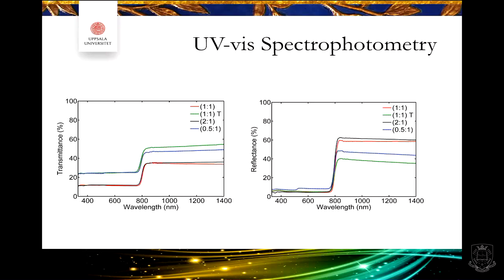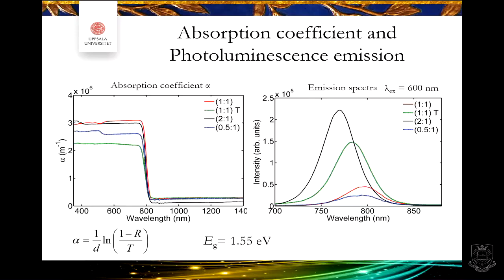And it's actually not transmitting so much, but you see this line, this is the band gap. And what is a little bit unusual for this material is also that you have a very sharp band gap when you do the perovskite directly in solution. Very, very organized. Now I continue.